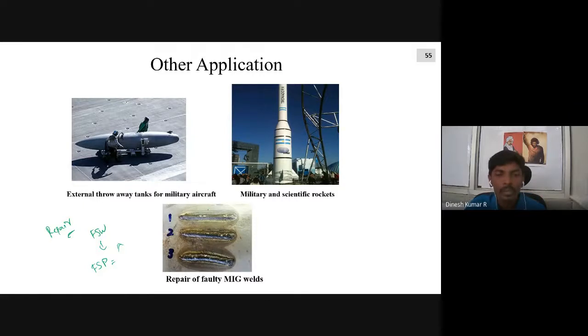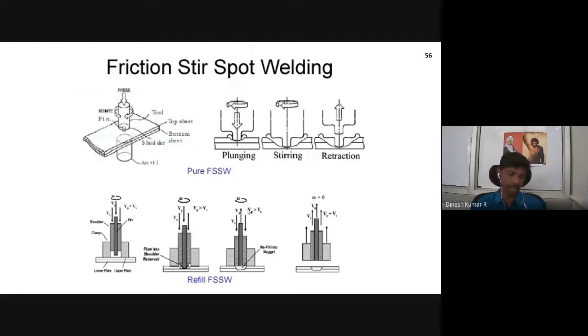Now in a normal fusion welding process, if we get some defect, a blowhole or something, instead of throwing away that weld or reworking it, if you go for FSW over that welded zone, it will reform your defects and you will get better weld strength there. So that is also possible right now. All right, this is completely about friction stir welding. Another technology available is friction stir spot welding, which Maruti and Hyundai are mostly adopting now.